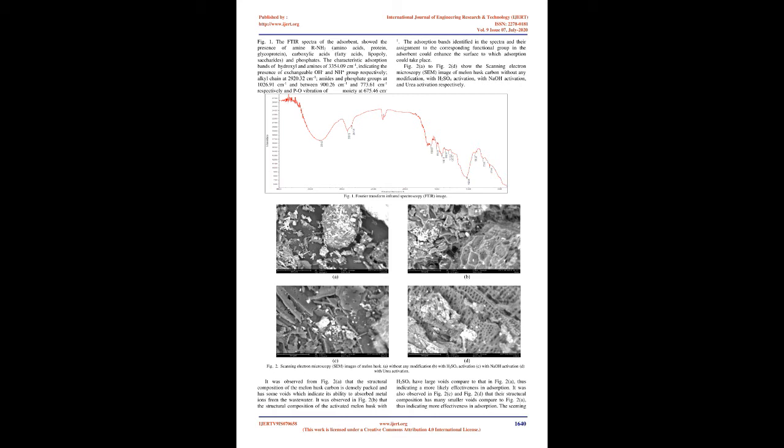C. Scanning Electron Microscopy, SEM. The surface texture and morphology of the carbonized melon, Citrullus colocynthis, husk was determined using scanning electron micrograph. The availability of pores and internal surface is a requisite for a potential adsorbent. To observe the surface pore structure of the activated carbons, SEM studies were carried out using an electron probe microanalyzer, model JEOL JXA840A, Japan. For char samples, the foremost requirement was that they must be moisture-free. The pulverized sample was mounted onto a substrate with a conductive adhesive. Coating with a thin film of conducting material was the primary requisite for all non-conducting specimens to be examined in SEM. In the present study, coating of the specimen was done with gold metal by vacuum evaporation to get uniform thickness of the specimen during analysis.